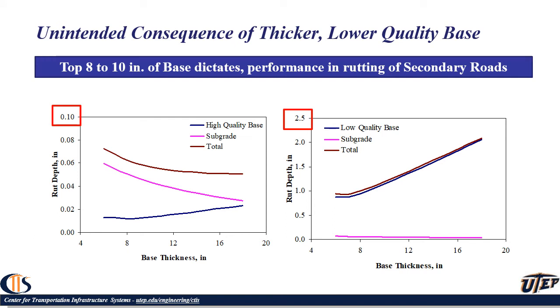One thing that I have in mind: when I'm using the high quality base, the maximum rutting I'm showing is 1/10 of an inch. When I'm talking about the low quality, I'm talking about 2.5 inches of total rutting. For the high quality base, as you increase the thickness, the total rutting decreases, as you see over here. Because as you increase the cover with thicker bases, you increase the rutting insignificantly in the base, but you significantly decrease the settlement, the rutting in the subgrade.